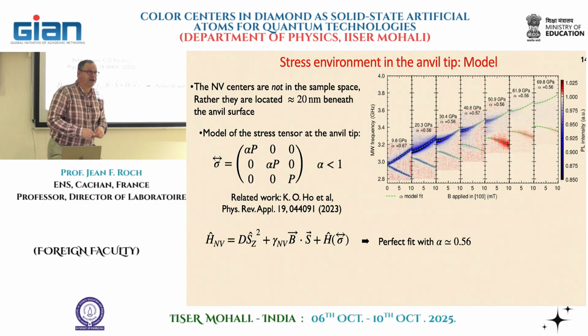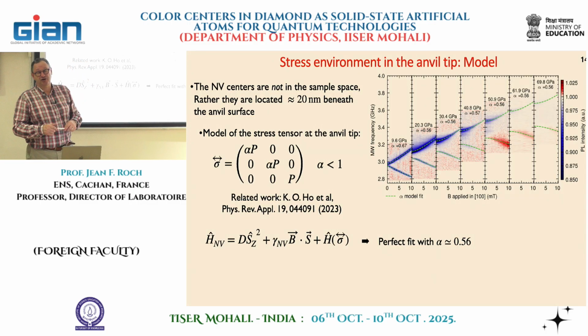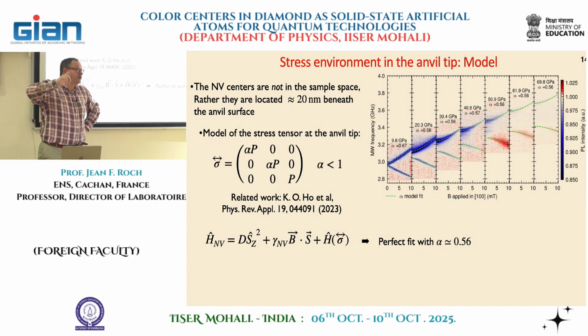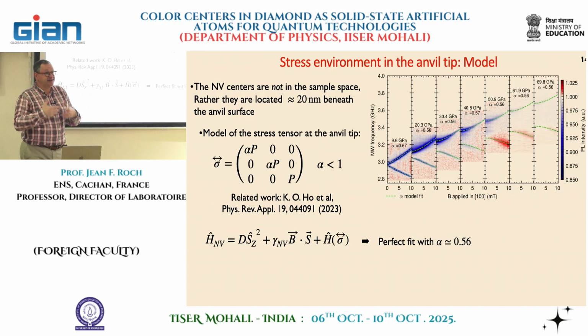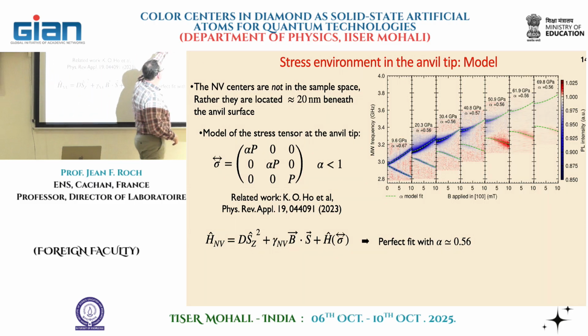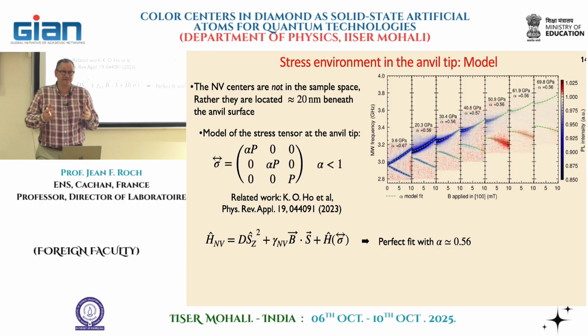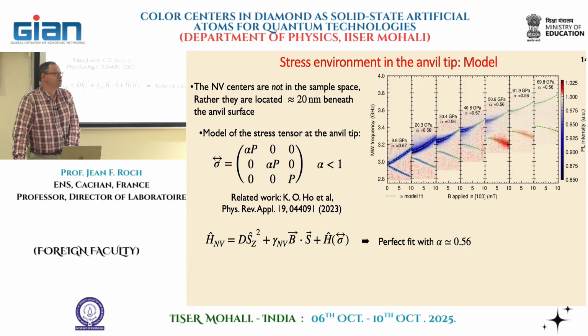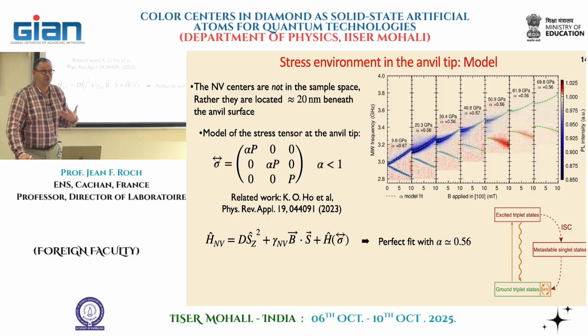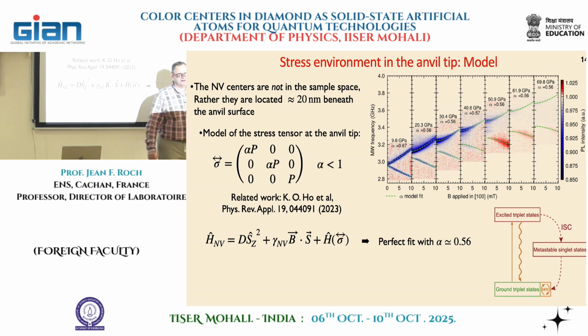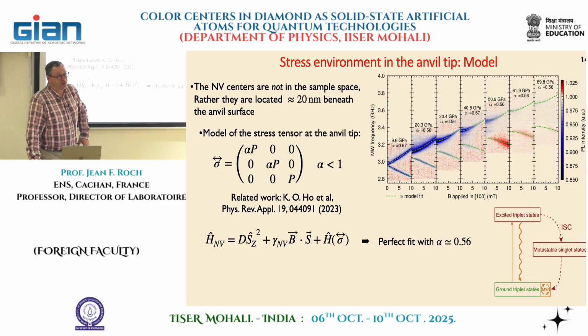But at the same time, the non-hydrostatic stress, the transverse component of the stress, will mix the quantum states, the basis states ms equals 0, plus 1, and minus 1. And this induces this shape dependence. We also believe, though we do not have a model for that up to now, that this will induce the decrease of the ODMR contrast due to this strong mixing effect. But this we don't know. We would have to reproduce everything we know, especially the intersystem crossing and the metastable singlet state. Unfortunately, we were not yet able to do it. We don't know how non-hydrostatic pressure affects both the singlet state and the intersystem crossing rate.